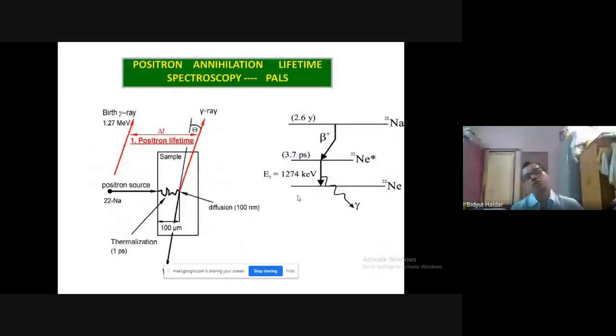In positron annihilation lifetime spectroscopy, we take sodium-22 as our positron source, which emits positrons and has a half-life of 2.6 years. As soon as the positron is emitted, it comes through the excited state of neon, which has a very small lifetime of 3.7 picoseconds. This excited state of neon comes to the ground state of neon by emission of a gamma ray of 1.274 MeV. So this gamma ray, when it is detected, announces the birth of the positron, because it can be taken almost simultaneously.